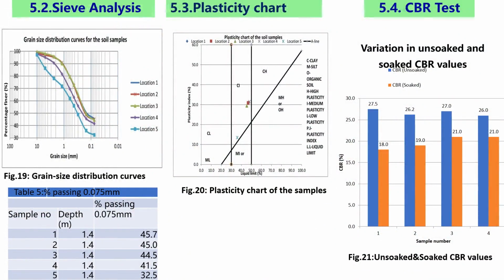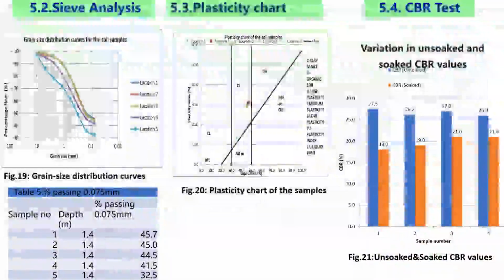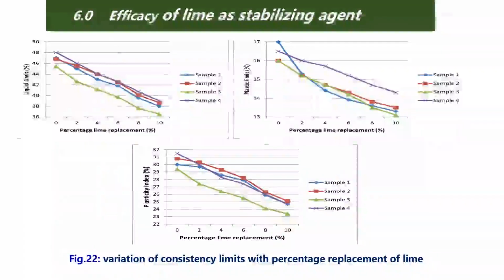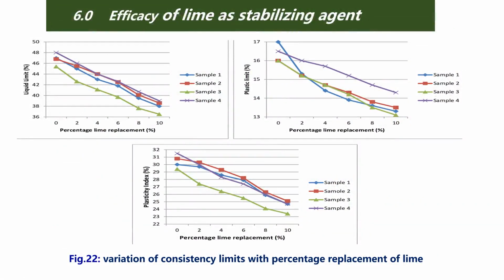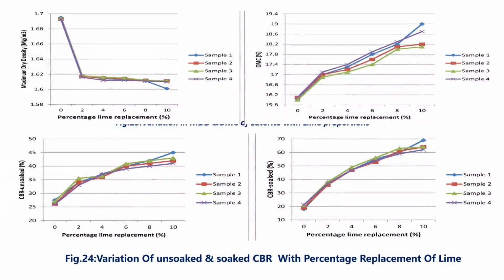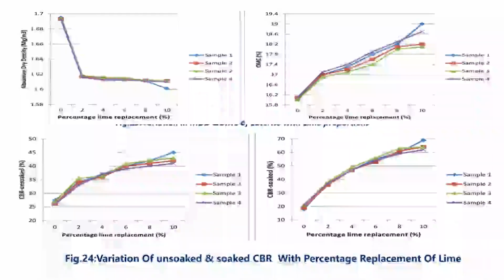Now, the effect of lime as a stabilizing agent was investigated, and from these curves, using consistency limits, that's the liquid limit, plastic limit, and plasticity index, there is a general trend of decreasing liquid limit with higher lime content. Also for maximum dry density and optimum moisture content, there is a general decrease in maximum dry density with a corresponding increase in optimum moisture content. And for California bearing ratio, for both soaked and unsoaked, there is a general trend of increasing California bearing ratio values with increase in lime content.